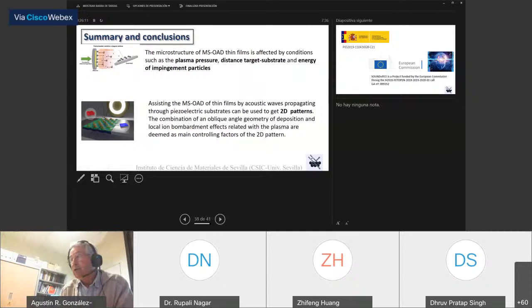With that, I would like to arrive to my conclusion very simply. I would like to vindicate the use of magnetron sputtering in an oblique angle deposition simply by saying that it is very critical to control the deposition conditions like plasma pressure, distance target substrate, and energy of the impinging particles. If we don't control these parameters, we may have results which are not in line with the nanostructuration that is expected for oblique angle deposition.